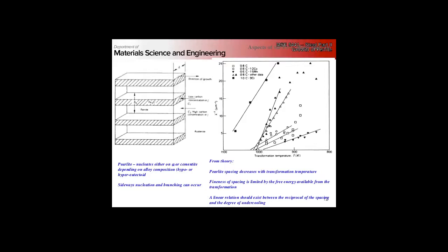Yeah. So did you just say when there's diffusion, the diffusion is faster, and then it ends up being wider? The lath becomes wider because it takes a longer time to get up to a carbon concentration. And then in the online one, you said increased temperature slows down growth and lowers the interface. Yeah, the interface itself is moving slower, so you're partitioning slower, but you're diffusing faster. So that means a wider spacing between nucleation events, right?